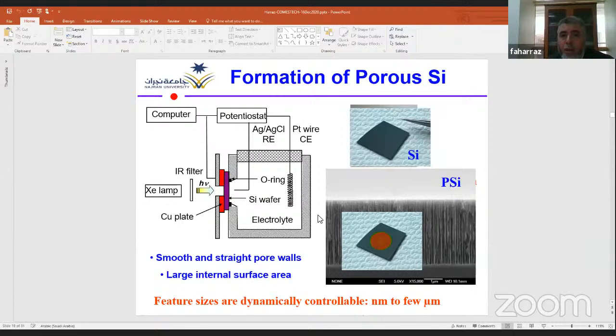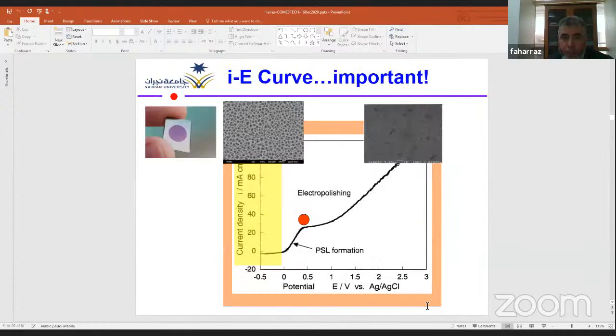This just shows you how to form porous silicon starting from a silicon wafer by electrochemical anodization in hydrofluoric acid containing some alcohol or surfactant. Optimizing the electrochemical etching and anodization, we can obtain smooth and straight pore walls together with an extremely large internal surface area. And with just simple playing with the conditions of the electrochemical etching, controllable pore sizes ranging from nanometer up to a few micrometers can be attained.